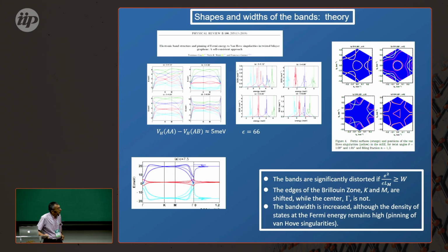That was already noticed by Paula Mellado and Laura Rademacher. This means that you create a strong electrostatic potential as you go away from charge neutrality, creating a significant change in the band structure, because it affects electrons near the K and the gamma point differently. So depending on which states are filled, you will have a higher or lower charge density wave or Hartree potential, which in turn will affect different states in the moire unit cell in different ways.